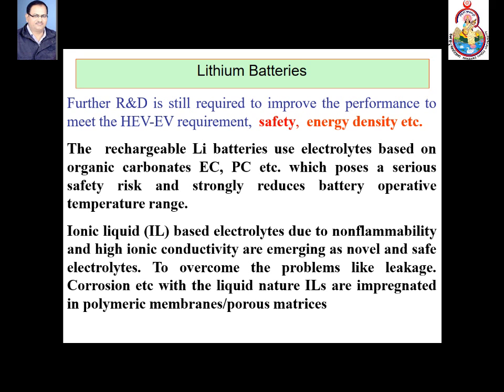Conventional lithium batteries use liquid electrolytes in which lithium salt is dissolved in conventional plasticizers like ethylene carbonate, propylene carbonate. However, these pose a safety risk, and therefore recently organic ionic liquids, which are non-flammable and have high conductivity, are being used in place of conventional organic plasticizers. These ionic liquids, besides providing ionic charges for conduction, reduce the degree of crystallinity of the polymer matrix.